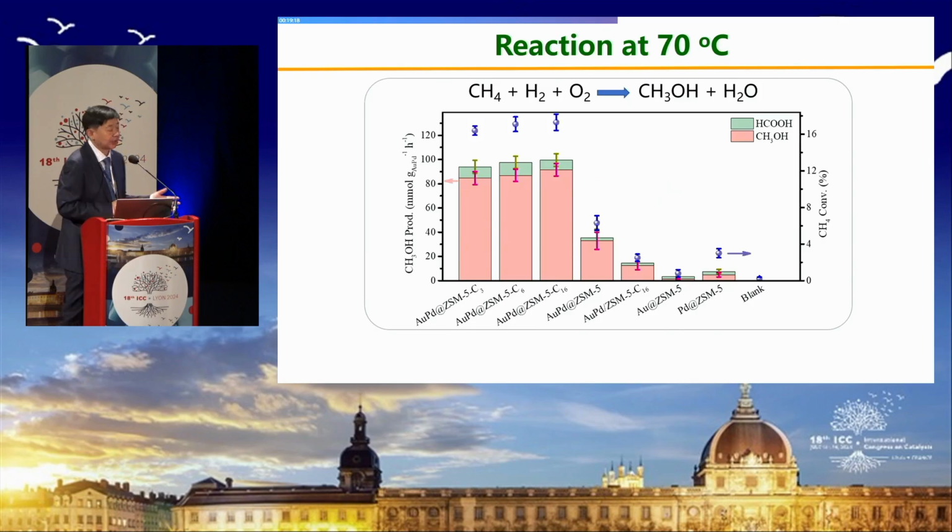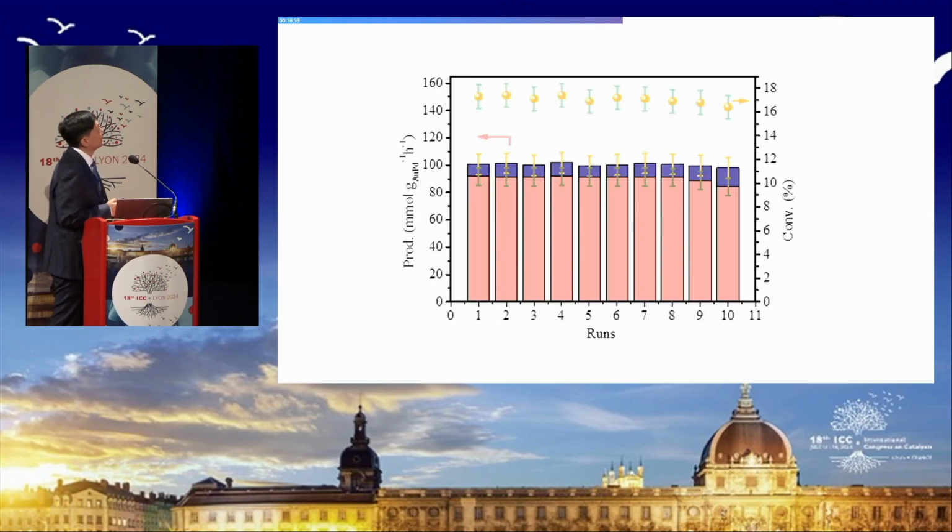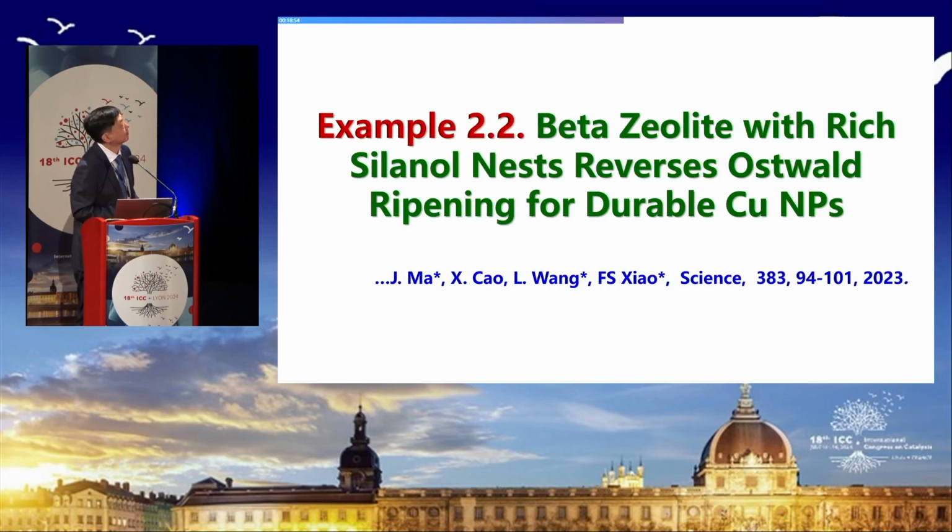In this way, you can compare the activity. Without the molecular fins, it is almost inactive. But after construction of molecular fins, conversion is very high, selectivity over 90%, and conversion higher than 17%. How about stability? Recycled 10 times, almost no change.